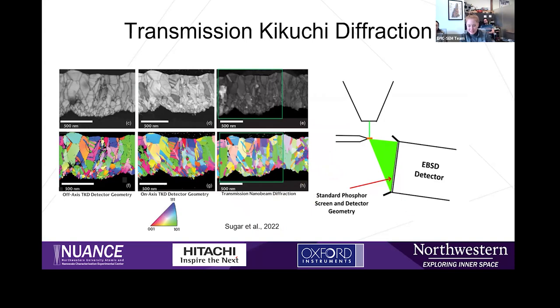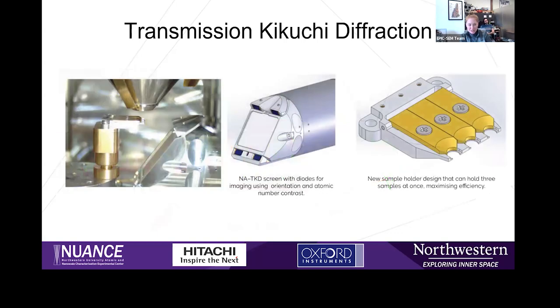One of the exciting things that is coming up that we don't technically have on this instrument, but we hope to have in the future: Oxford just introduced at the Microscopy and Microanalysis Conference their new near-axis TKD screen. This screen gets inserted on the head of the EBSD detector on the Symmetry 3, which we will have on this microscope. You can see it's not on axis, but it's near axis. Overall for transmission Kikuchi diffraction, this can increase the sensitivity by decreasing distortions in the pattern. It will be very fast, so you can do high throughput analysis, and it just overall improves your spatial resolution.